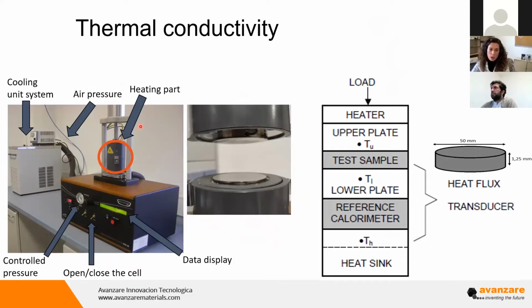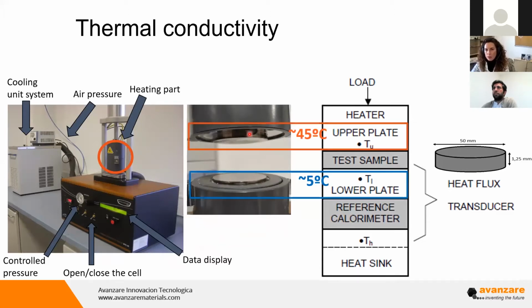This is the one that we have at Avanzare, and I'm showing you in a video how we technically do the measurement. This is with a cooling unit system to keep this plate at cold temperature, about 5 degrees Celsius, while this upper plate is heated to about 45 degrees. So here inside we have some thermocouples to determine the voltage and, with that, the temperature.